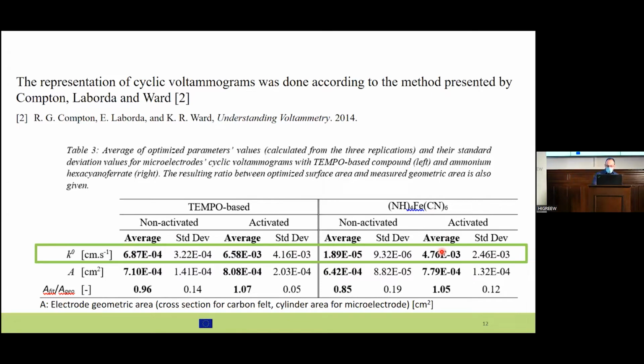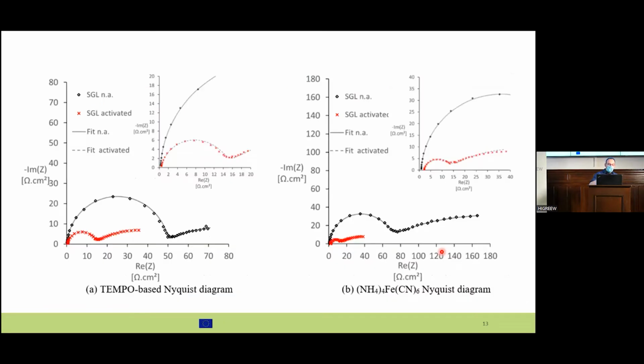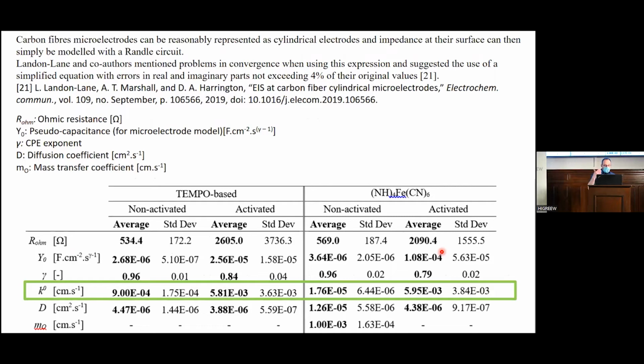In order to check the accuracy of the measurement, we completed it with electrochemical impedance spectroscopy. Again, I am not an expert in this method. This is my colleague. We do the analysis also with a model described in the literature recently by a PhD student in Australia, and we get a fairly similar value as in the previous table. So we are confident that this microfiber, with its simpler geometry, allows a more accurate analysis. This is great. It means that now we have a more accurate method to screen the material and to see the effect we want to study in this HIGREEW project.